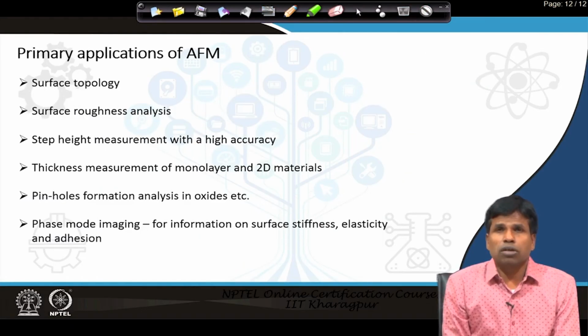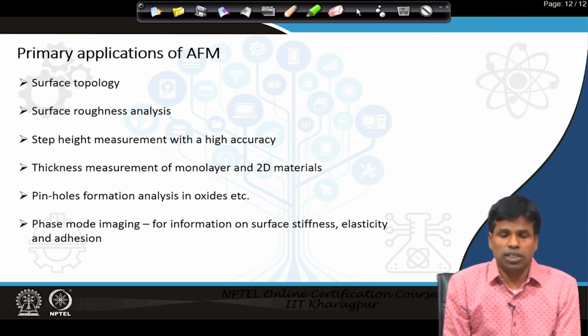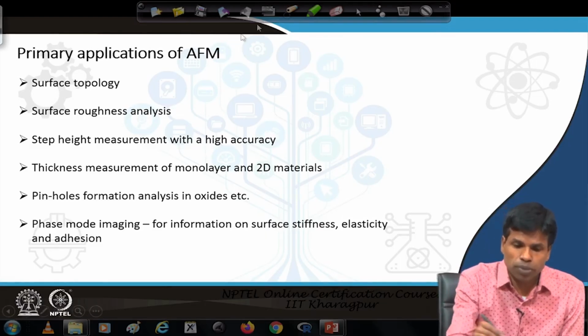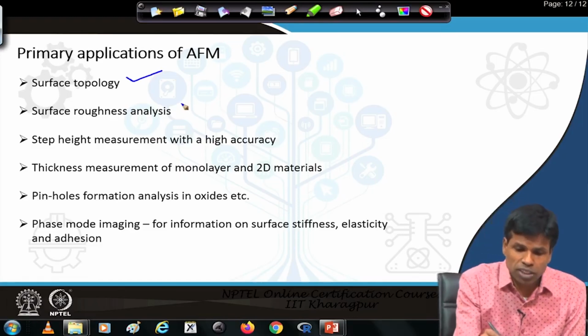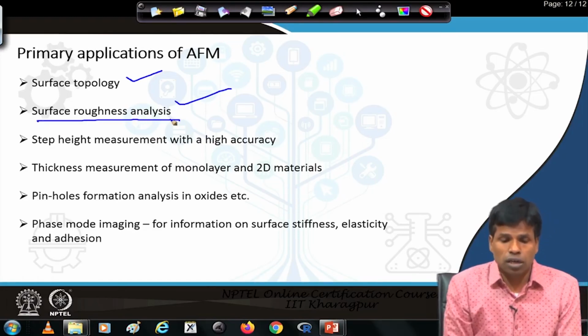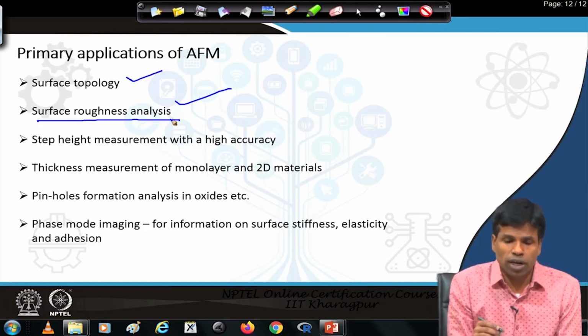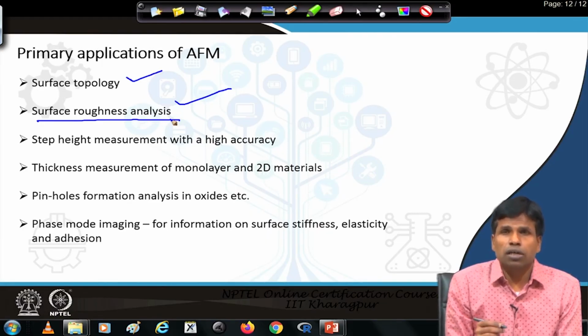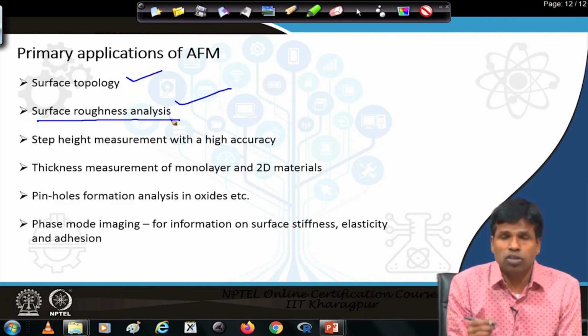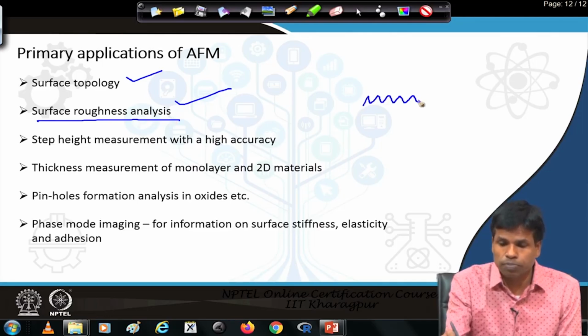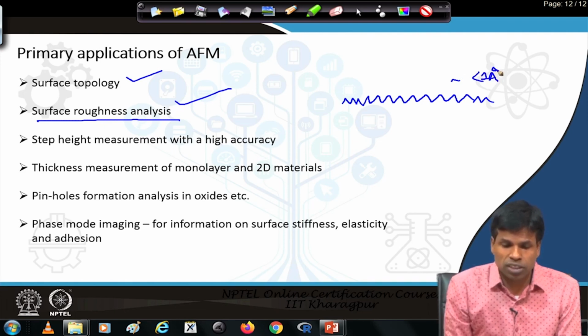Primary application of the atomic force microscope, as we see mostly by students in research laboratories or in academic laboratories, is to measure the surface topology, 3D features of the surface. Surface roughness analysis is most commonly done by this technique when we want to measure the RMS roughness, or root mean square roughness, in a small area. So, accurate surface roughness can be detected, the height or roughness range at a sub angstrom level, less than 1 angstrom, one can measure surface roughness.